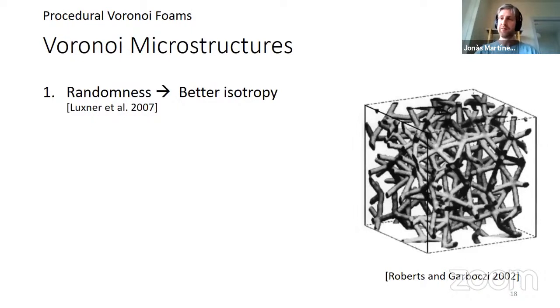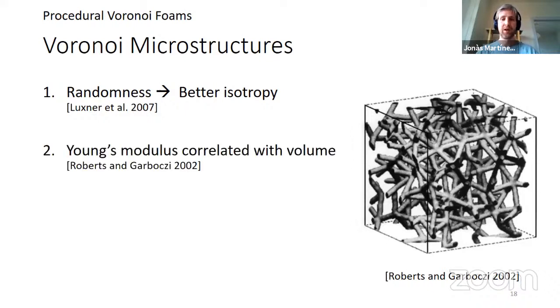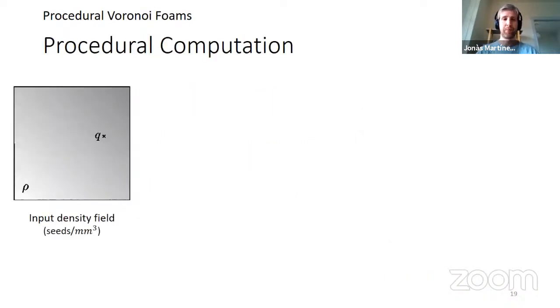And we dived a little bit more, and we saw that there were already several studies on Voronoi microstructures. It's interesting because when you consider a small piece of the space, it's been shown that the randomness actually helps to get a better isotropy for a finite extent. Also, we got interested because the Young modulus is correlated directly with the relative volume. However, the Poisson's ratio remains quite stable and positive.